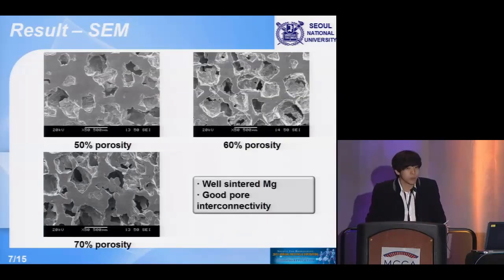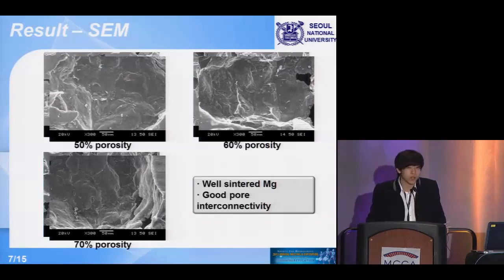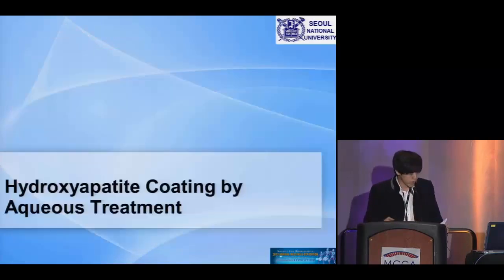And these are the SEM images, surface SEM images of the porous magnesium, and you can see that it has very good pore interconnectivity. And with the higher magnification, you can see that magnesium has been well sintered without visible boundaries of the magnesium powders. And now is the hydroxyapatite coating part.